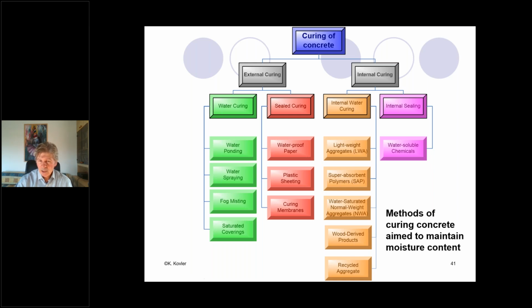But please look, even normal weight aggregates like sand can be considered as an internal water curing agent when this aggregate is introduced in the concrete mix in water saturated condition. Wood-derived products, including different byproducts of the wood industry, and recycled aggregate, which is porous, by the way. Internal sealing methods are still on the research laboratory shelves. We have this method described in several papers, but it's still far away from being implemented in the industry. But these methods, especially lightweight aggregates and superabsorbent polymers, especially the first one, are already in practice.